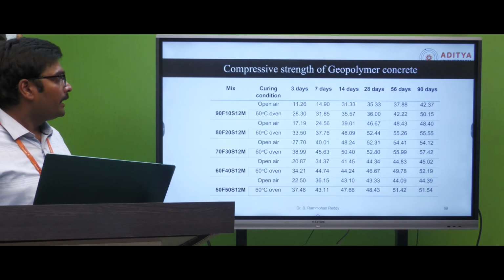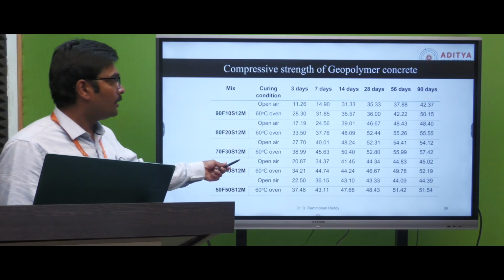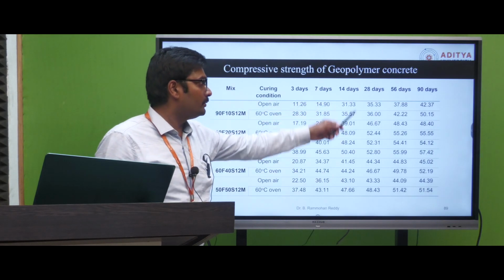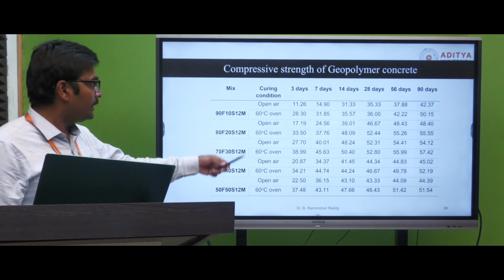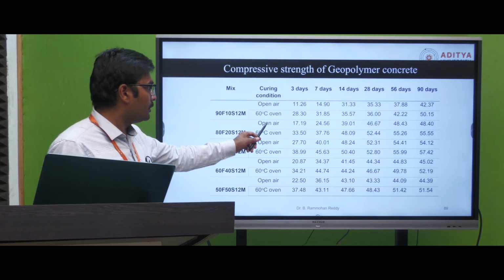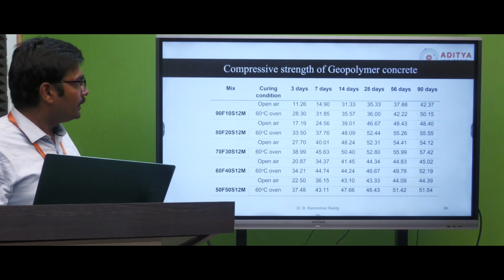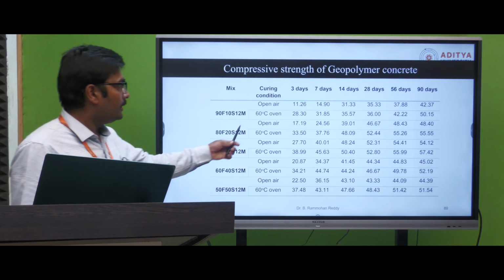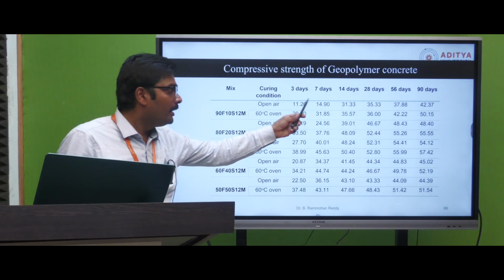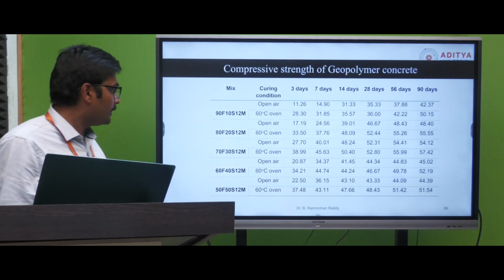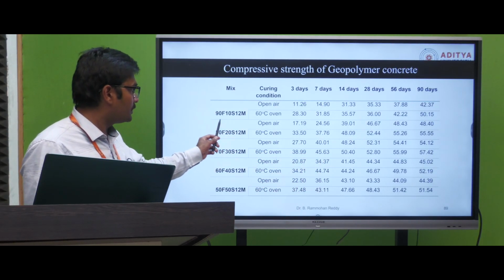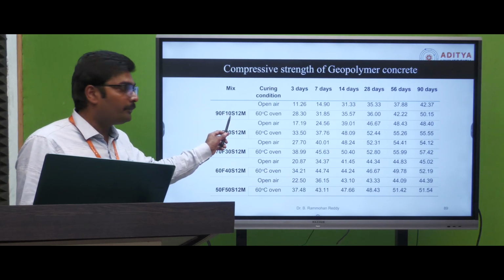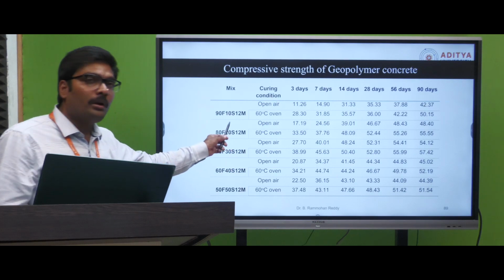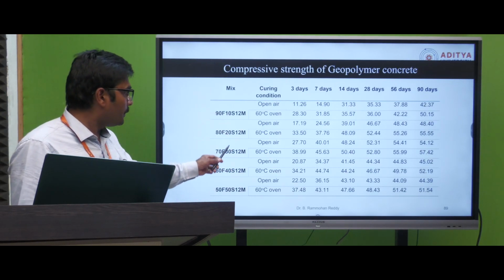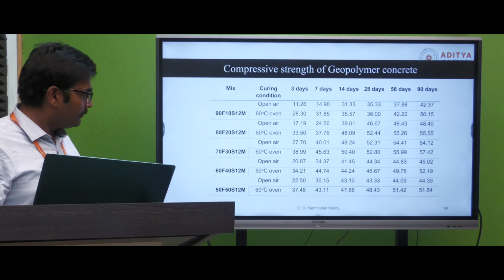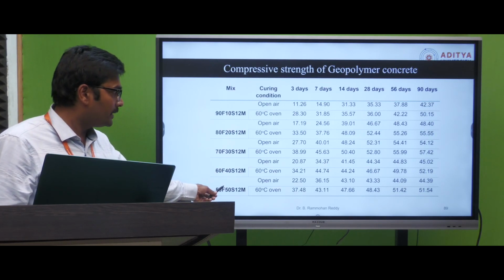And in another study, he presented the compressive strength of geopolymer concrete at 3 days, 7 days, 14, 28, 56 and 90 days, and he presented different curing conditions also, like open air curing and 60 degrees oven curing. He presented that, compared to open air curing, 60 degrees oven curing produces better compressive strength values, which you can compare here. Also at different proportions, for example 90% fly ash, 10% silica fume and 12 molar solution. All of these use 12 molar NaOH solution, and different combinations of fly ash and silica fume proportions were presented here.